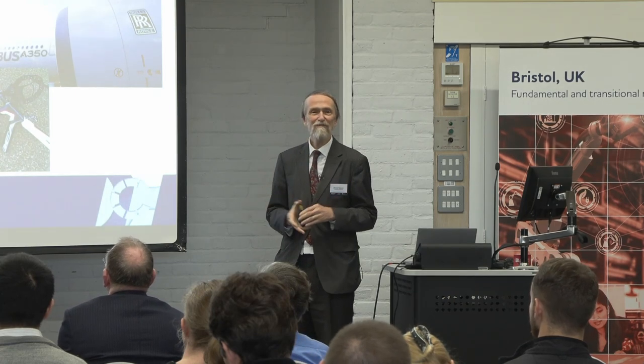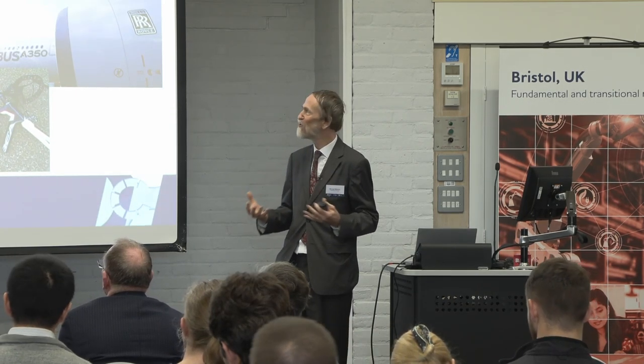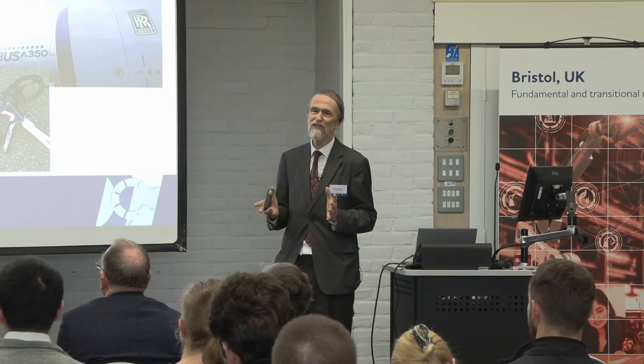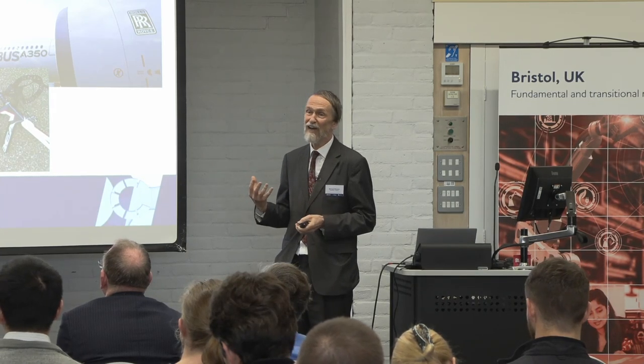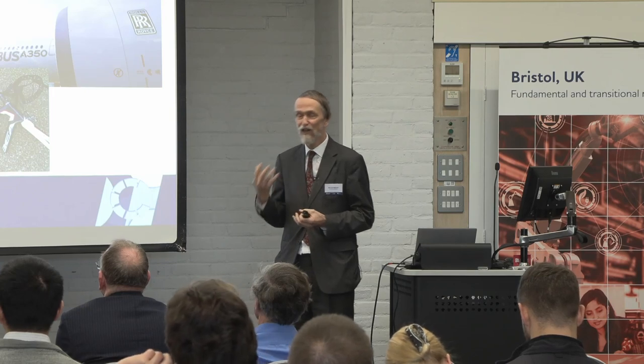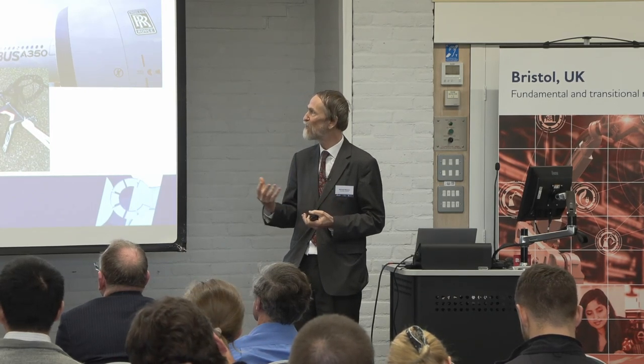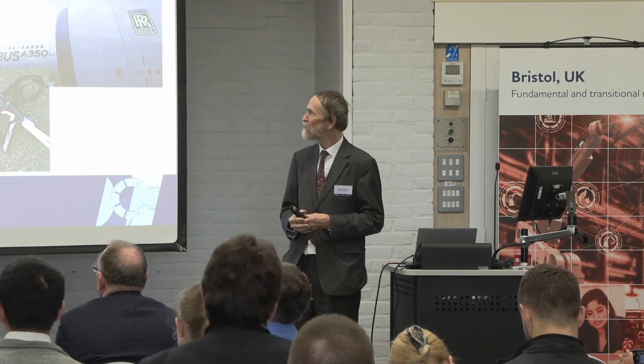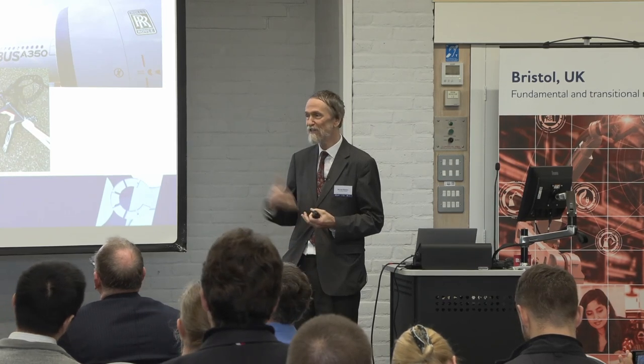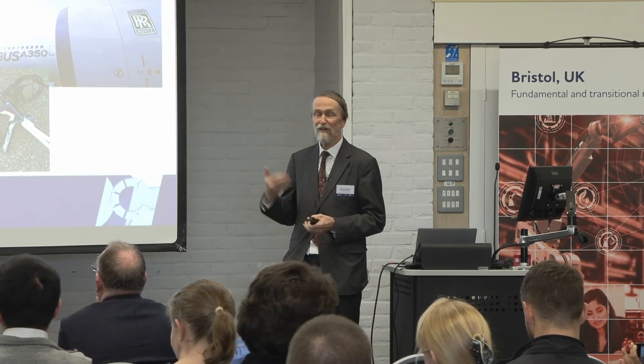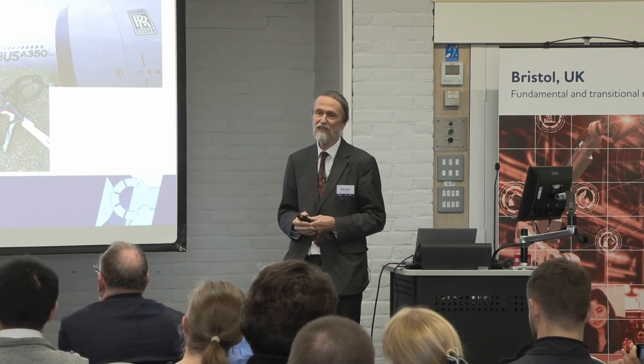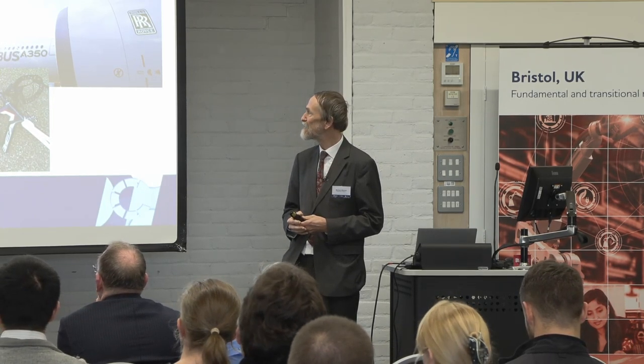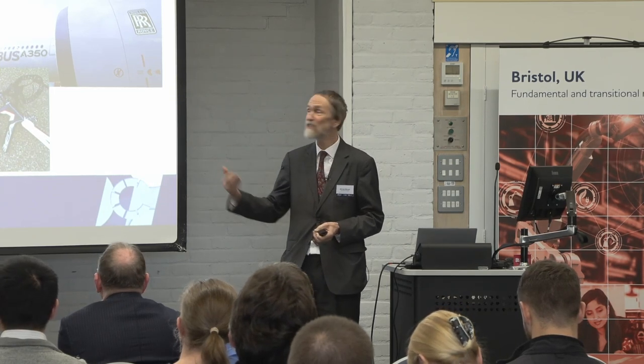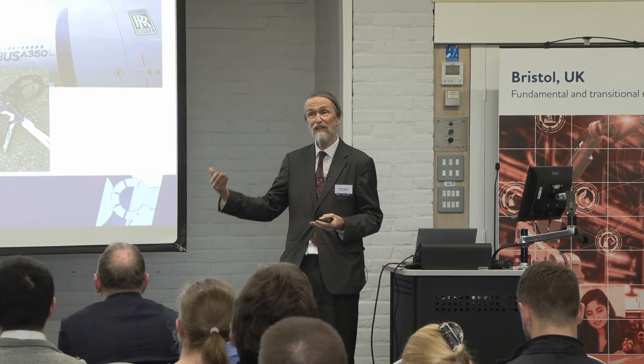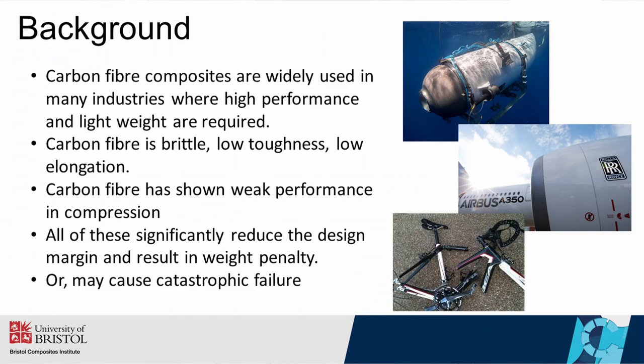So carbon fiber composites are wonderful materials. They're stiff, they're strong, they're light, they're durable. But one of the issues is that they tend to be brittle, and we can have relatively low failure strains and relatively brittle behavior. So this can also affect the ability to exploit these materials. Compressive strength is another key limitation of carbon fiber composites, and this can lead to weight penalties and potentially catastrophic failures. So how can we address these problems and try to improve the behavior?